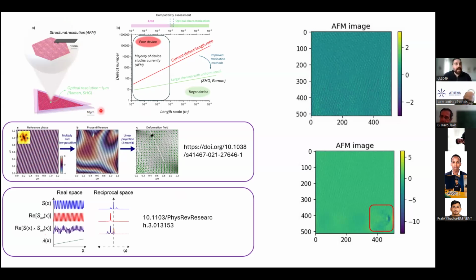Let me mention that two-dimensional materials, especially TMDs, have very high nonlinear susceptibility, second order nonlinear susceptibility. And you can use polarization resolved second harmonic generation to probe their twist angle very accurately. So what we are trying to do is understand this method here, which is geometric phase analysis. Basically, you have moiré images, or maybe it's simpler in the one direction case. You have a non-perfect periodic wave, and then you multiply it with a perfect periodic wave, and if you low pass filter it, you end up with a phase of your local wave, let's say.